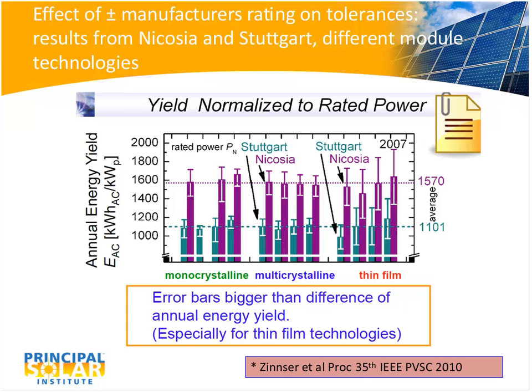But if you look at them, you see an average over on the right, for example, of 1570 kilowatt hours per kilowatt, but to try to draw meaningful distinctions between them and say, is one module better than the others, you look at the error bars there and you see that, first of all, the error bars certainly straddle any difference between the modules in either location, and also in particular the thin films have much bigger error bars associated with them than the crystalline silicon, although even with the crystalline silicon some of them are significant. The error bars are larger than the difference between any of the technologies. The error bars arise from the uncertainty that I mentioned before in terms of the binning, because these are using the rated power, the manufacturer's rated power that you would have paid for that module.